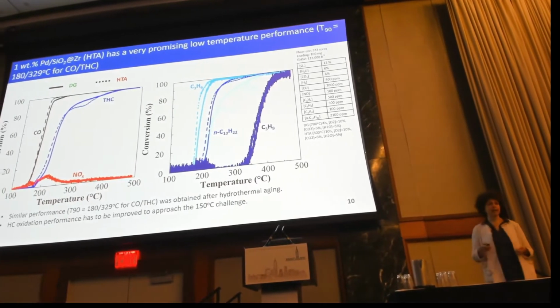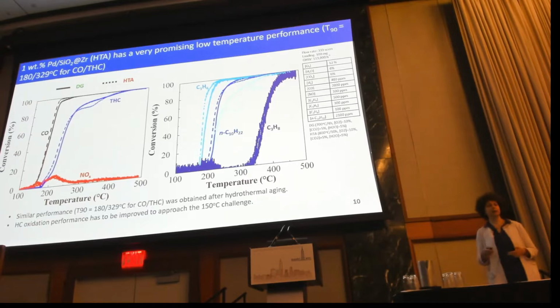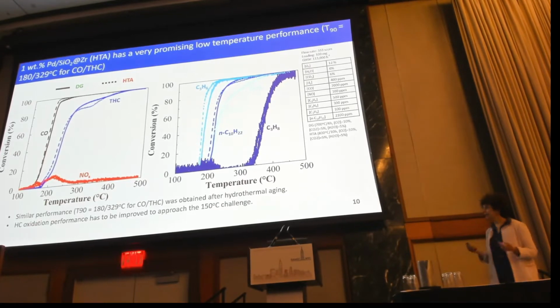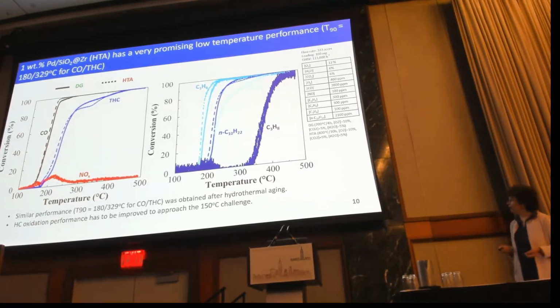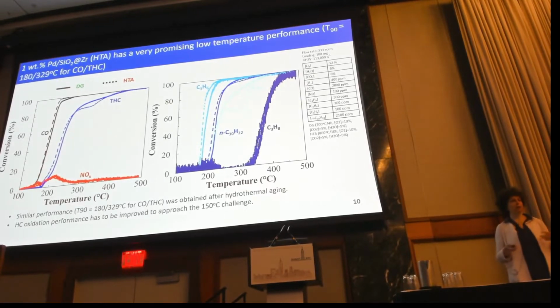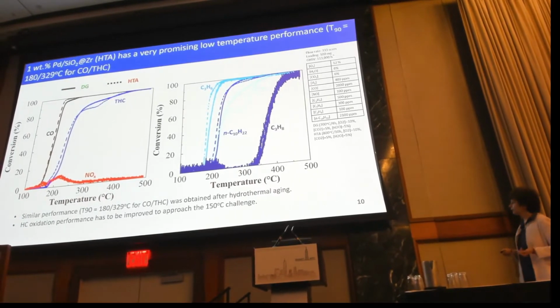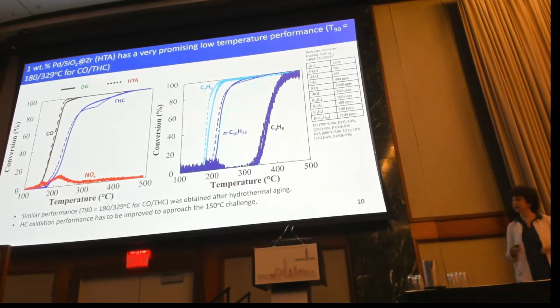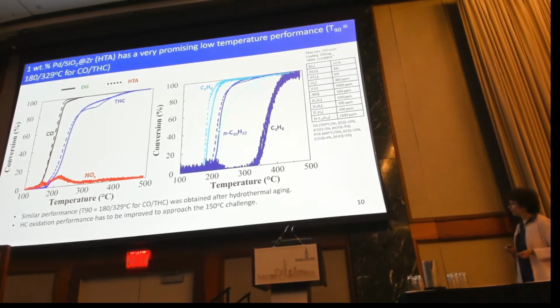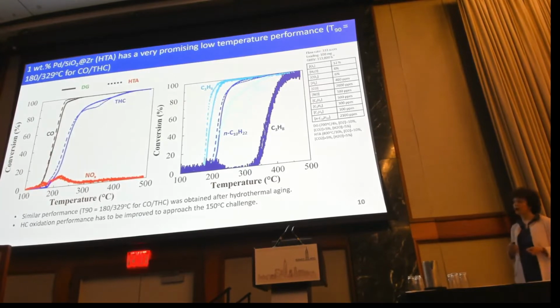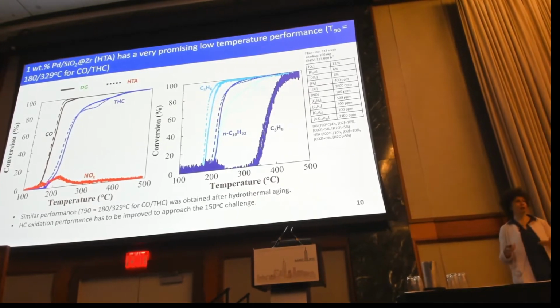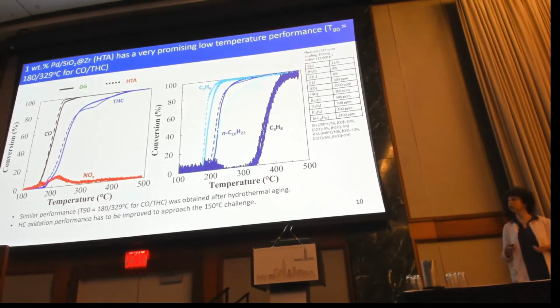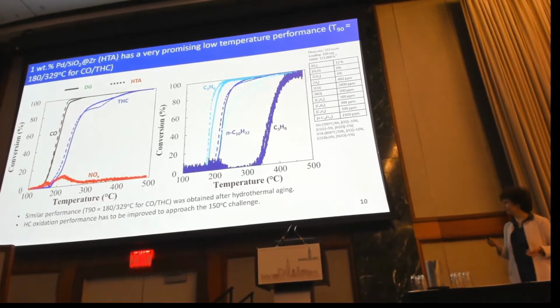So we're looking at this data, and of course we got excited by the fact that this catalyst is thermally stable. And this work is already published, but we want to improve on this material even further. And so Julie started looking into literature, and she said, platinum is more active for hydrocarbon conversion, so why don't we create bimetallic catalysts? Why don't we add platinum on this material? And actually there is an additional benefit because platinum currently is cheaper than palladium, so we're going to reduce the cost of the catalyst as well.